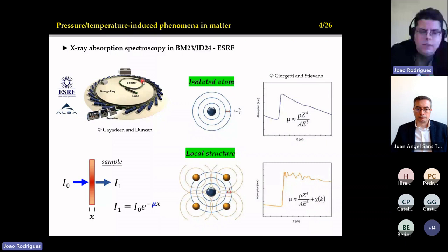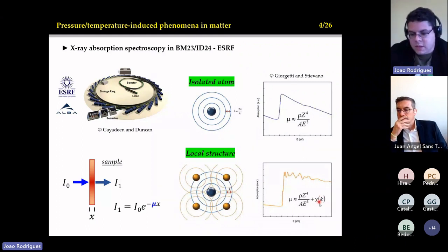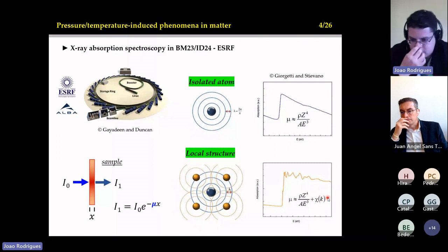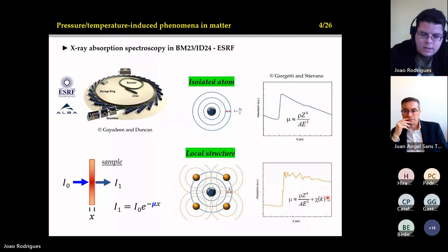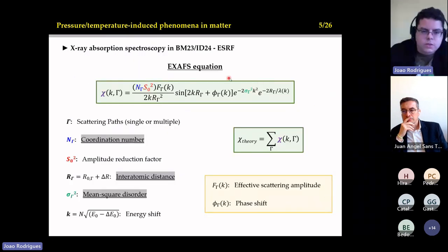So basically the idea is to investigate the local structure around the target atom. In this case, for example, I isolate an atom, let's say cobalt, and if there is nothing around, you see only the X-ray absorption coefficient like that, in this figure. But if you have some local structure, you start to see oscillations. We call this oscillation chi of k. And these oscillations are very important because you can later model this signal using the so-called EXAFS equation.